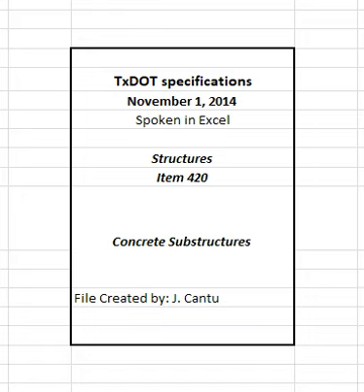Place concrete in columns monolithically between construction joints unless otherwise directed. Columns and caps or tie beams supported on them may be placed in the same operation or separately. Allow for settlement and shrinkage of the column concrete, if placed in the same operation, by placing it to the lower level of the cap or tie beam, and delay placement between 1 and 2 hours before proceeding with the cap or tie beam placement.